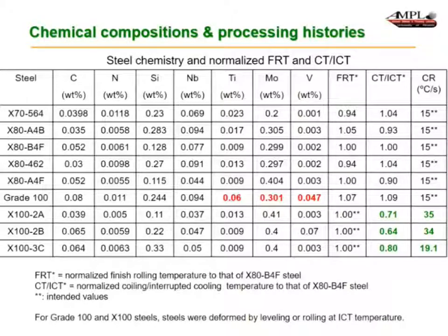Now, turning our attention to the niobium carbide precipitates, this is looking at the various steels that were looked at. Now, it's been known for years that niobium carbide contributes greatly to the yield strength of these steels. They've been characterized in terms of their size, their location, but when you look at these numbers here, they're very small. How much do they actually contribute to the strength of the steels in a quantitative way?